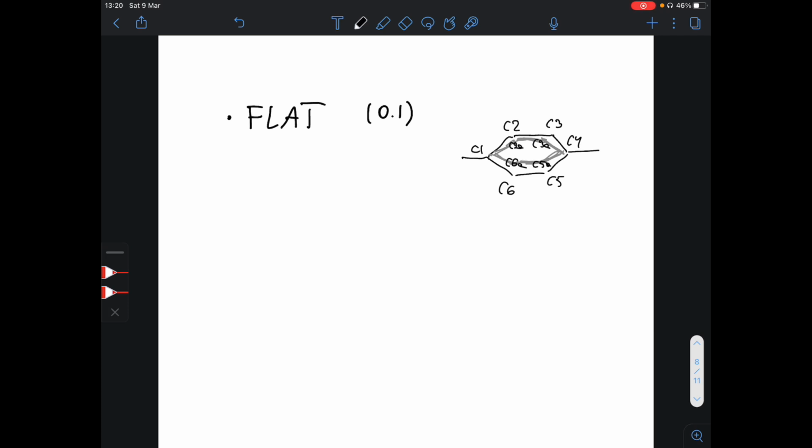So after inputting some restraints on appropriate 1,2 and 1,3 distances, we can also make sure that they are in one plane, because, well, a phenyl substituent should be planar, right?